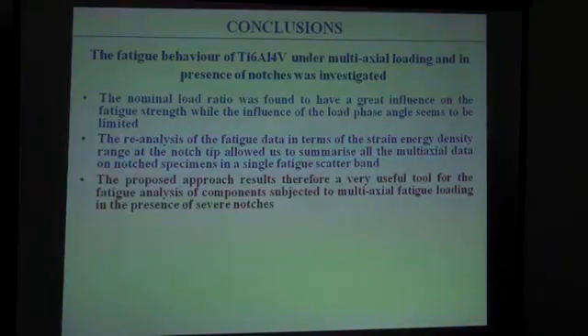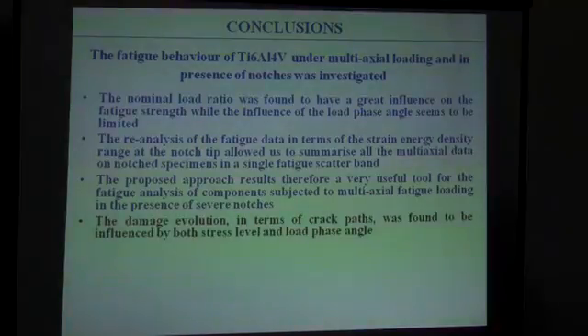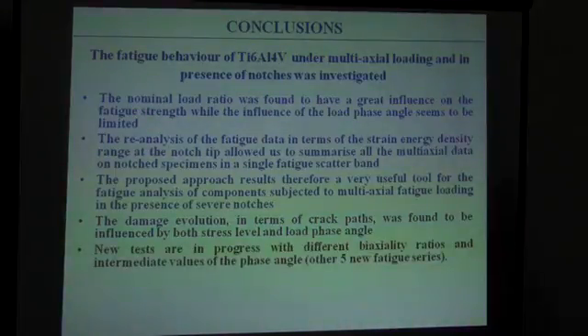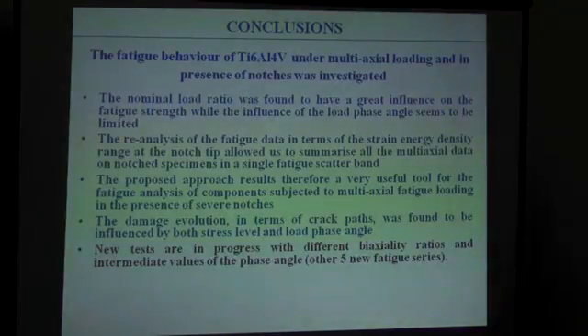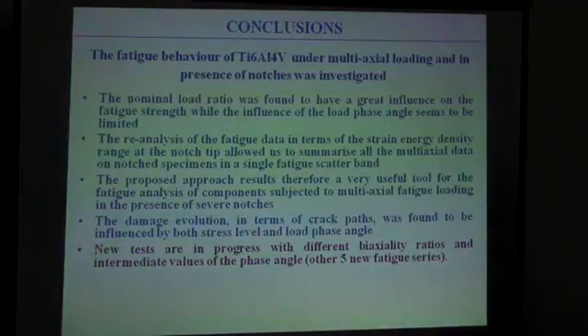Our criterion is not able to take into account the out-of-phase effect, because in this case the material is not sensitive to the out-of-phase loading, but if we have a strong out-of-phase effect, this criterion as applied here is not able to take this into account. It was possible to obtain a very good synthesis of the new results. Now in progress we have a different series with different biaxiality ratios and intermediate values of the phase angle. We are also changing the geometry of the notch to see if the phase effect is tied not only to the material but also to the notch geometries.